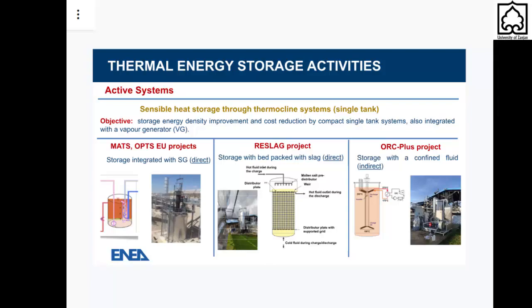And in this system, the tank is filled with a granular bed of blast furnace slag, let's say industrial waste, in direct contact with the molten salts, which come from, obviously, the solar field in the charging phase, or from the power block, obviously, in the discharging phase. Here, the objective is to reduce the cost of the storage system by reducing the amount of salts used for the thermal storage. And at the same time, we enhance the use of industrial wastes, so in a circular economy perspective.